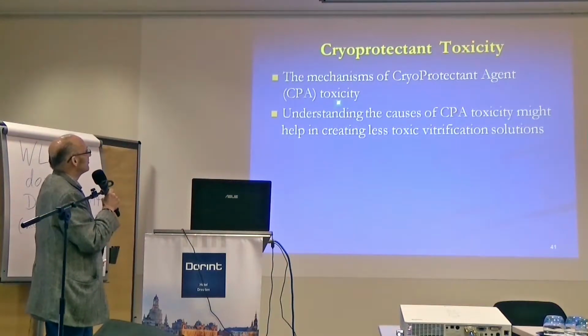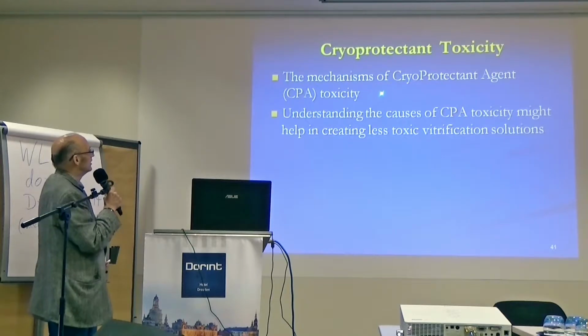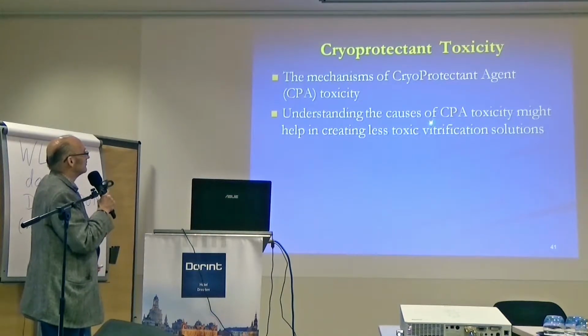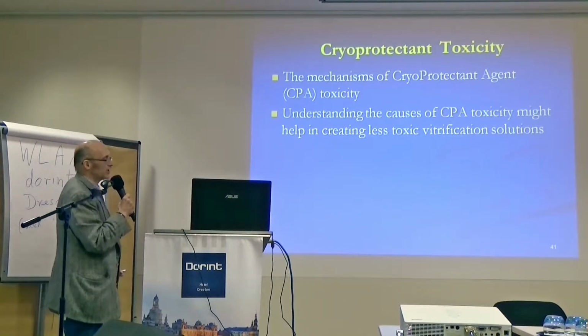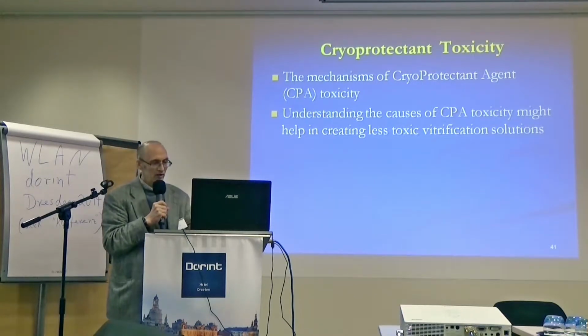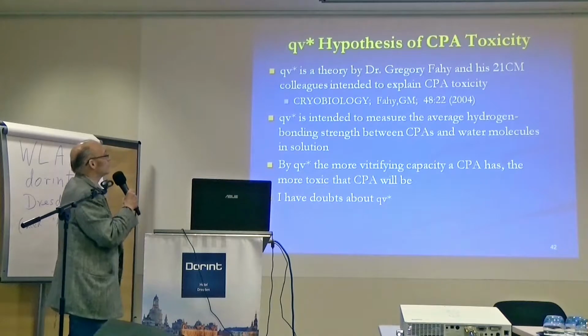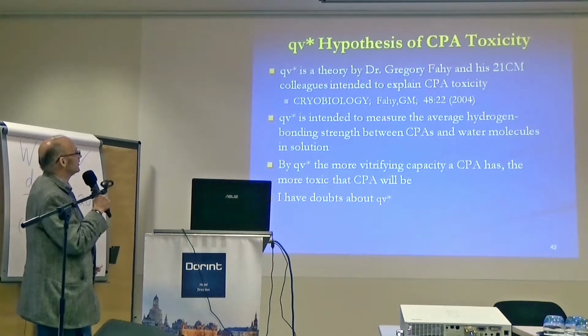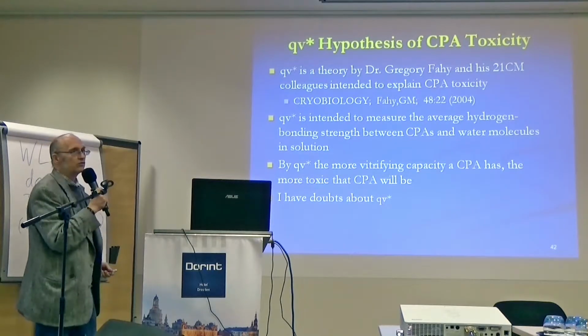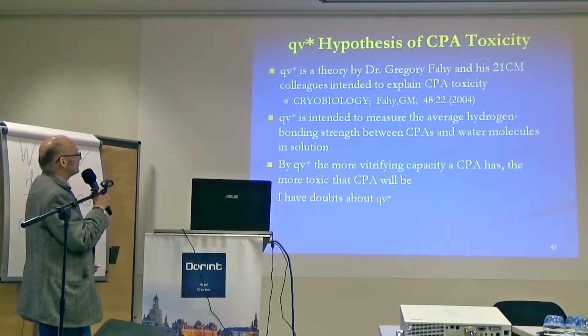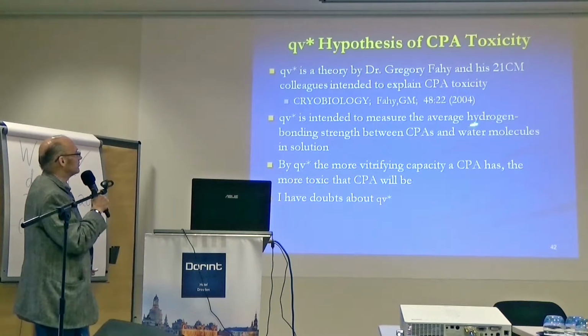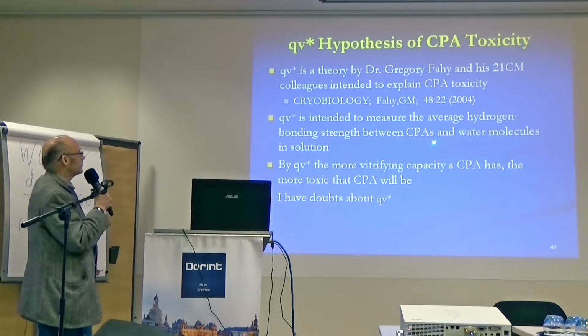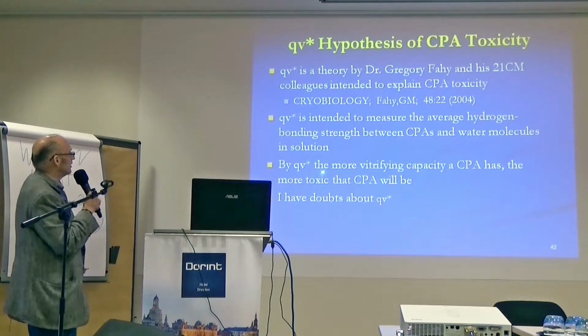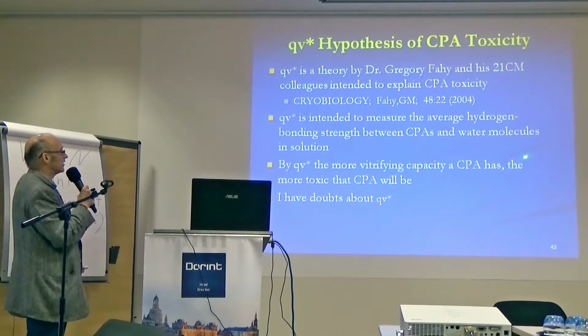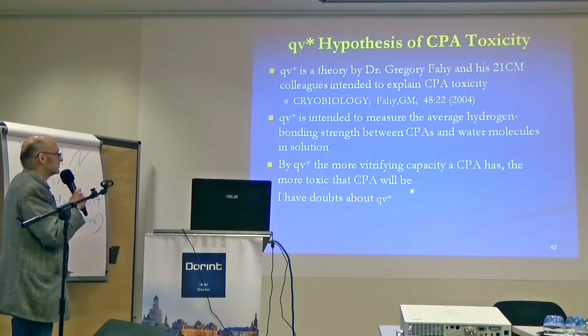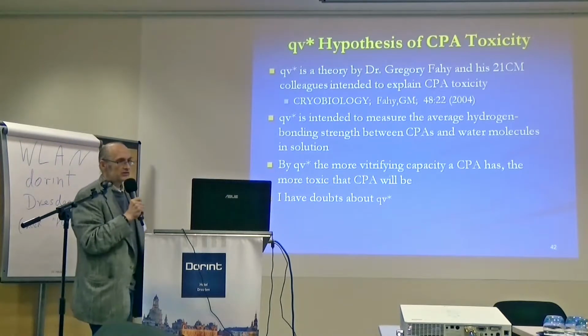But the mechanisms of cryoprotectant toxicity are not understood. There are some theories, but we don't really know. If we actually had an understanding of what the mechanisms were, that might help us to develop less toxic cryoprotectants. So Dr. Gregory Fahy and his colleagues at 21st Century Medicine have developed this QV star hypothesis to explain cryoprotectant toxicity. It's intended to measure the average hydrogen bonding strength of a cryoprotectant agent and water molecules in solution. By this hypothesis, the more vitrifying capacity a cryoprotectant agent has, the more toxic that CPA will be. But I have doubts about QV star.